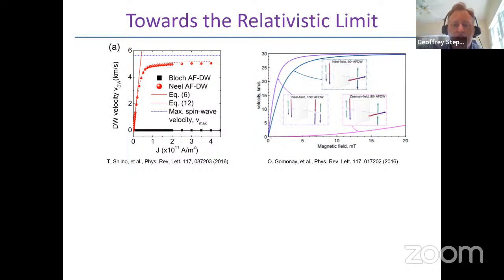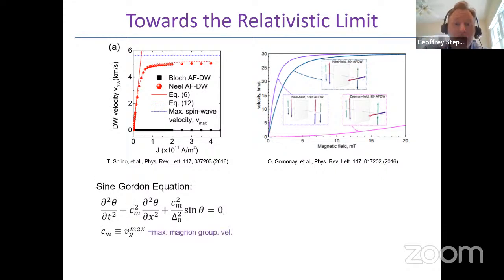Well, a domain wall is a soliton, and one can think of a soliton as built up as a superposition of spin waves or magnons that then travels in a system. And those magnons in a material will, depending on the material, have a maximum velocity. And anything that is constructed from this superposition should then also have a maximum velocity. So you might anticipate that the maximum velocity that any kind of solitonic structure could move should be limited by the maximum magnon group velocity. And one can actually show this in a variety of systems, that the dynamics at high speeds are described by a Sine-Gordon equation. And the Sine-Gordon equation has built into it a Lorentz invariance. There's a velocity that plays essentially the same role as the speed of light in special relativity.